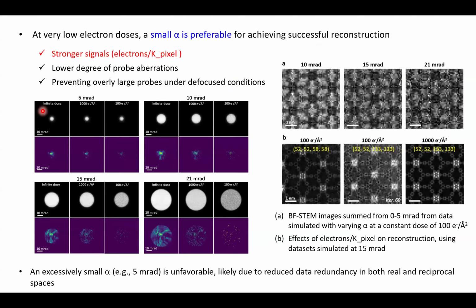I think there are several reasons for a smaller alpha being more favorable. First, for limited dose, a smaller alpha gave us stronger signals in the Ronchigram pattern. And at the same time, a smaller alpha also means a lower degree of probe aberration. It also prevents the generation of an overly large probe size under defocus conditions. So these factors are all favorable for reconstruction.